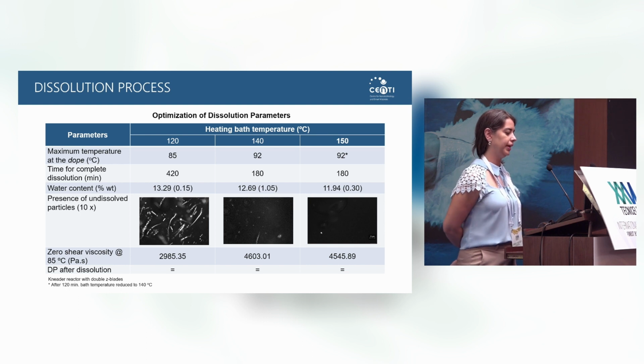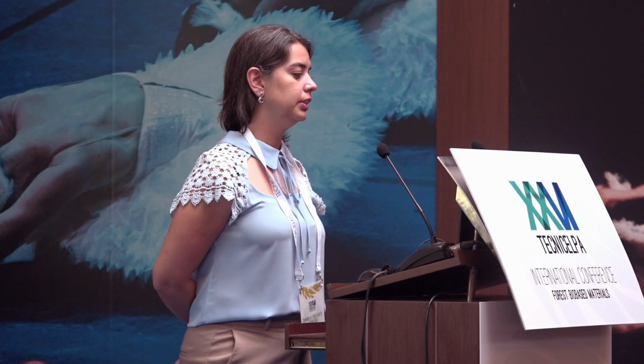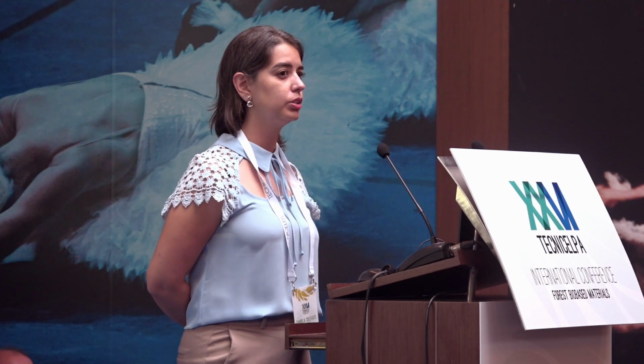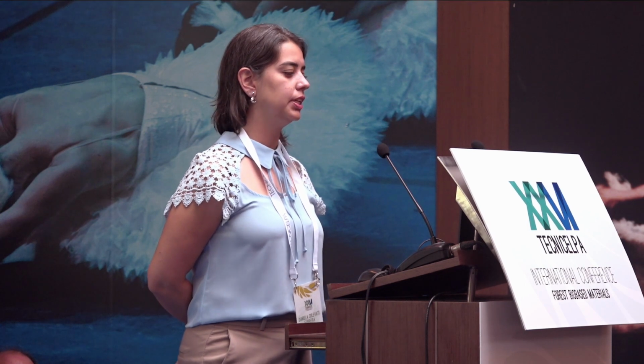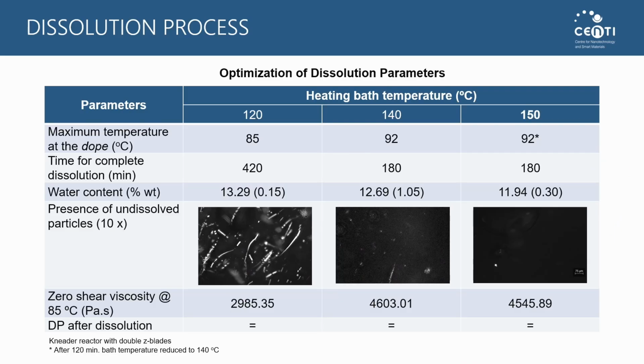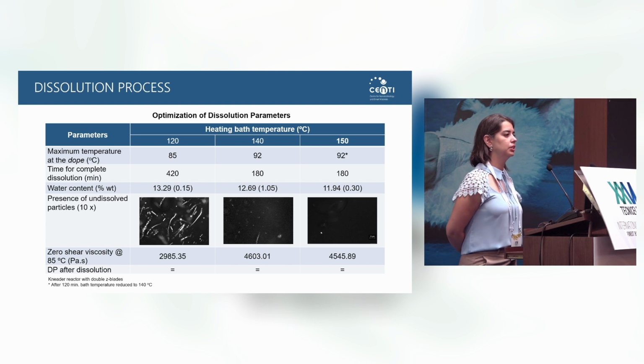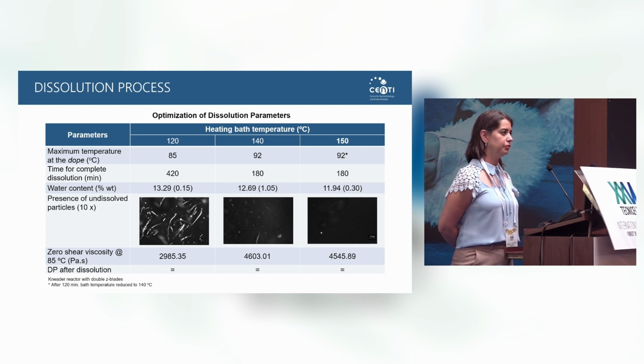We tried 120, 140, and 150 degrees, and monitored the temperature in the dope. At the lowest temperature, it was not the best one - we had a low temperature in the dope, and the time to complete the dissolution was very long, up to 420 minutes. At 140, we got the ideal temperature around 90 Celsius degrees, and the time was in an acceptable range for dissolution, 180 minutes. With 150 degrees, we got to the desired temperature faster, and after around 2 hours we had to decrease the bath temperature to avoid solvent degradation.